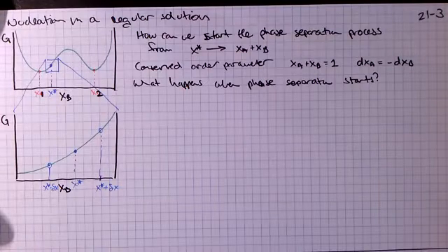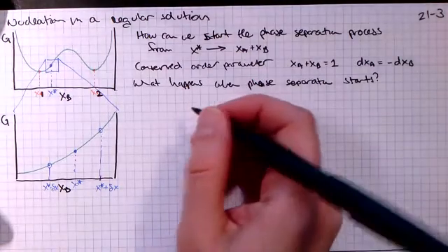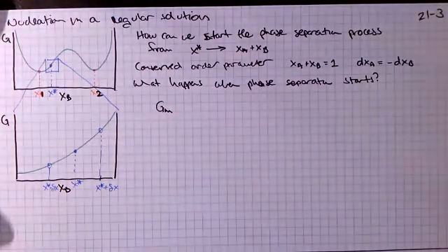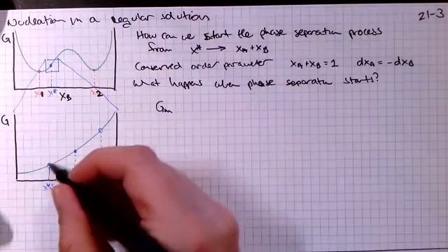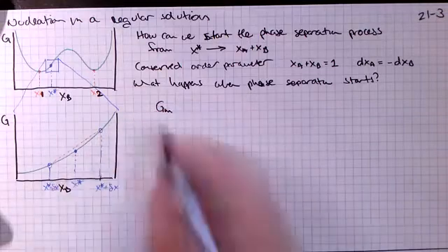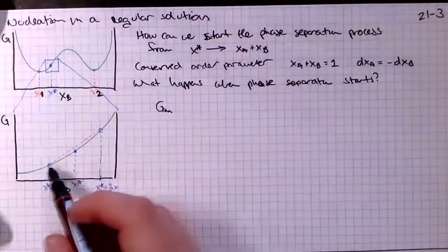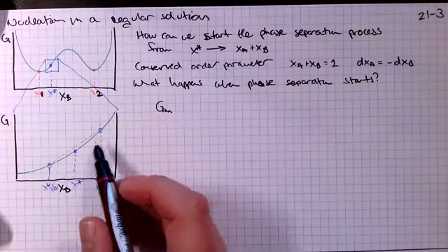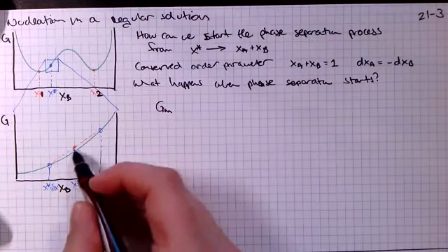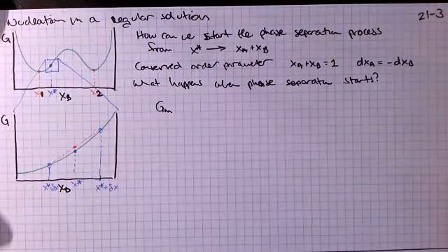Now, what we're going to notice is that when we do that, the free energy of the system per mole is going to equal some mixture of these two phases, and we know we can get the free energy of the whole system by drawing a line between them, right? Because if we're an average between these two, the total free energy per mole has to fall somewhere along this line. And so we can see graphically that our net free energy, in order to keep the composition at X star, is going to be above where the free energy was to begin with.